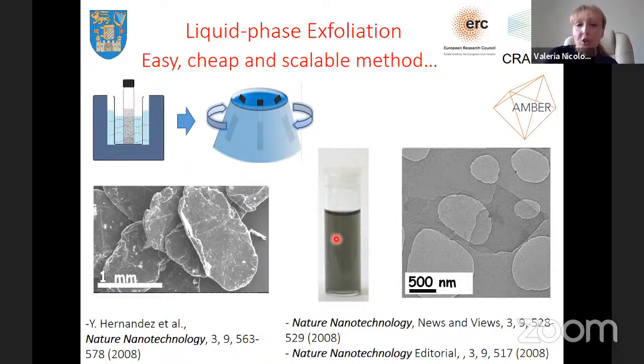When you do centrifugation, you end up with a very nice stable dispersion like this one that I show here in the center. And this is what we're going to talk about a lot later on in the talk, as I'm going to talk about this in terms of inks. This way of manipulating and processing the layered crystal into single and few layer sheets was really a revolution in a way that allowed us to produce these materials in quantities that are workable. And this is what we do in my group. We really use these materials now in real world applications. And this method here doesn't take more than half an hour.